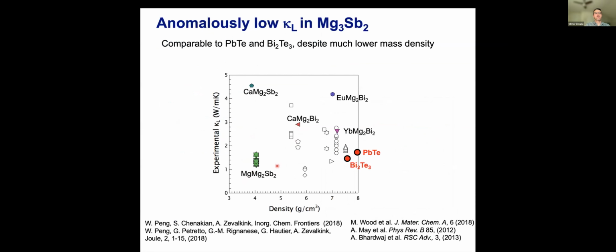So if you look at the magnesium 3 antimonide, it's got comparable or lower thermal conductivity than much heavier elements, lead telluride or bismuth telluride. So this is plotted on the density axis here at the bottom. You can see this is half the density, but similar thermal conductivity.